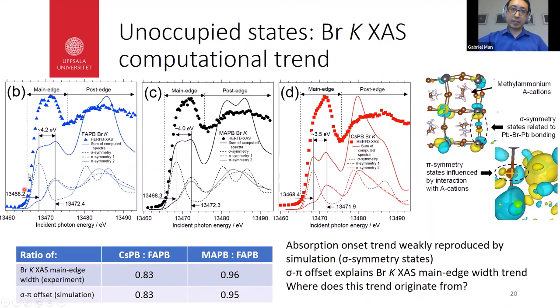One common feature for all three is that the rising edge, the lower photon energy feature, is all sigma symmetry states, whereas the pi symmetry states are all at higher energy. If we take the peak maxima, get the energy offset, and then take a ratio, we get something that exactly matches the ratio of bromine K XAS main edge widths. That suggests that the width of the main edge originates from the energy separation between these two distributions of states. Because the XAS spectrum is a reflection of the conduction band, this suggests that the conduction band width is determined by the sigma-pi energy separation.